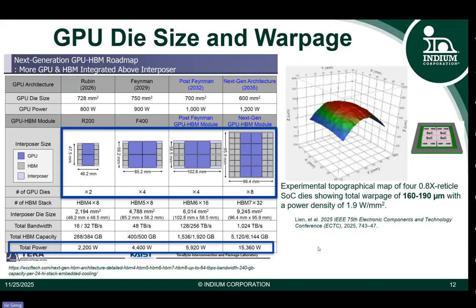On the right, you can see an example of how big the warpage can be for this kind of big assembly. The example showing here is a four 0.8X-reticle SoC dies. Putting it together, the total warpage can be 160 to 190 microns. So that puts a lot of challenge on the TIM materials.